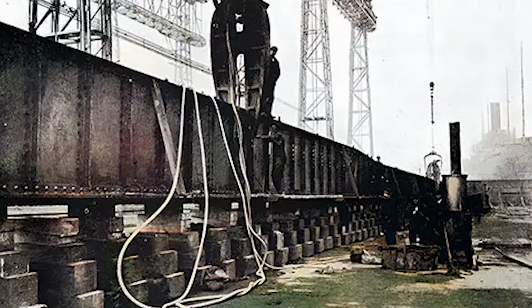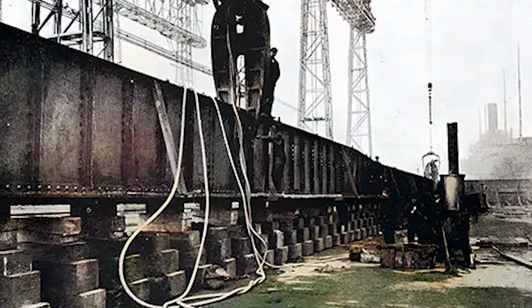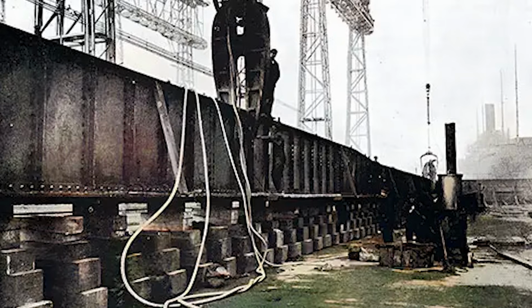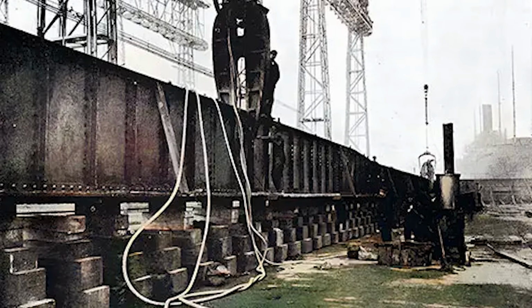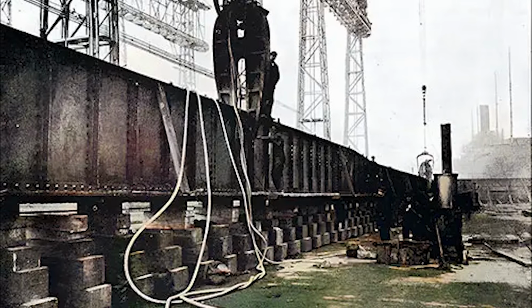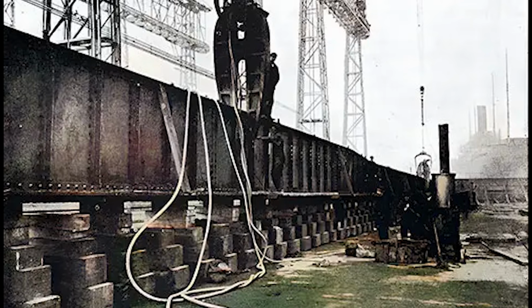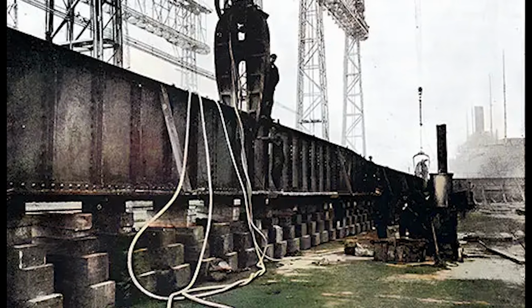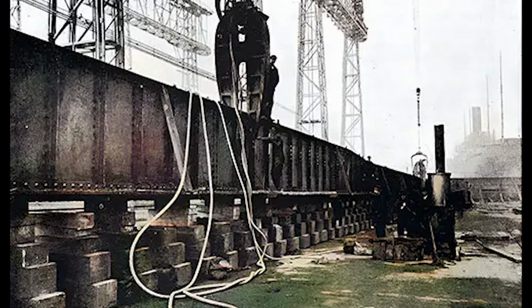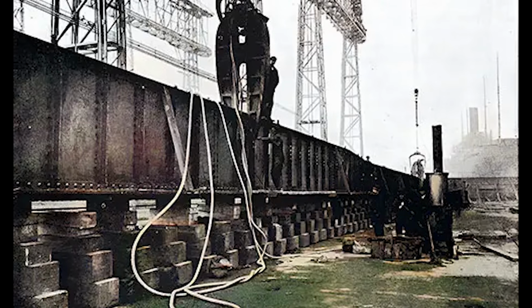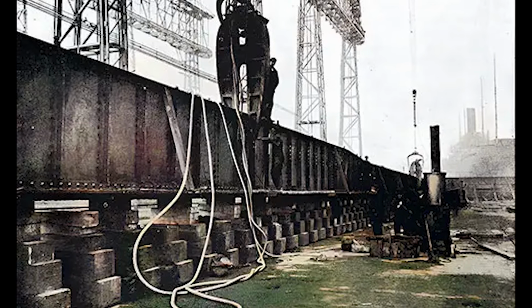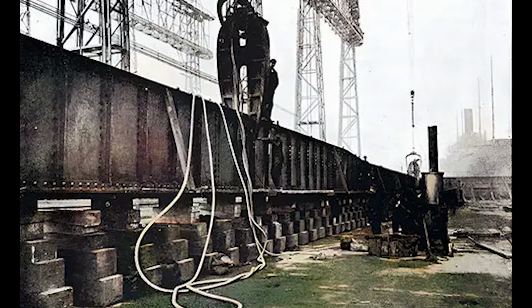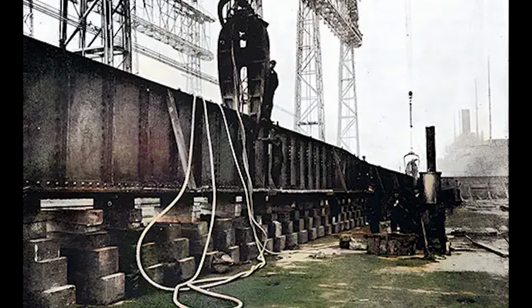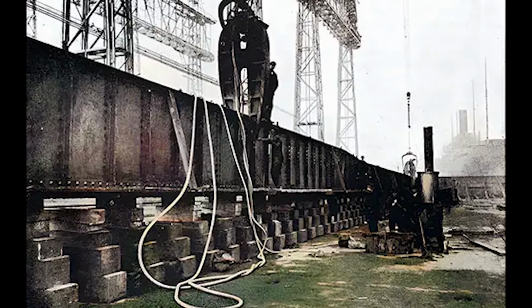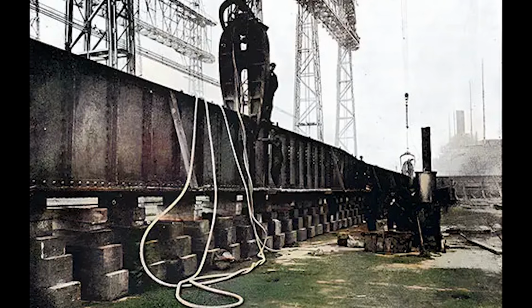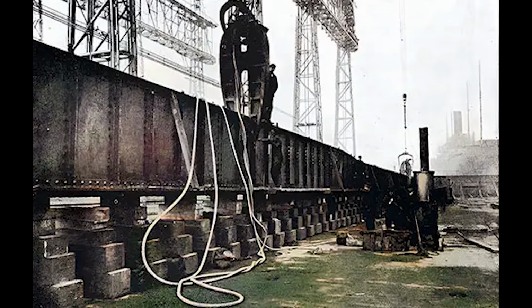The cascade of failures accelerated throughout winter months as more Liberty ships encountered the cold water conditions that triggered brittle fracture. By April 1946, 1,031 Liberty ships had been damaged by structural cracking, with 233 declared total losses beyond economical repair. The program designed to save Allied shipping through unprecedented production efficiency was destroying itself at rates that approached German submarine success during the worst periods of Atlantic warfare.